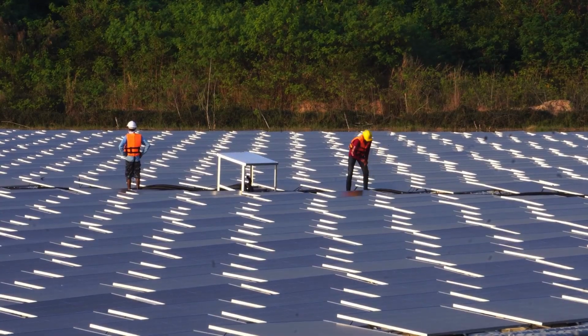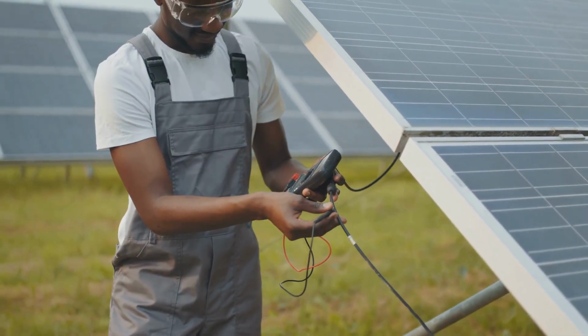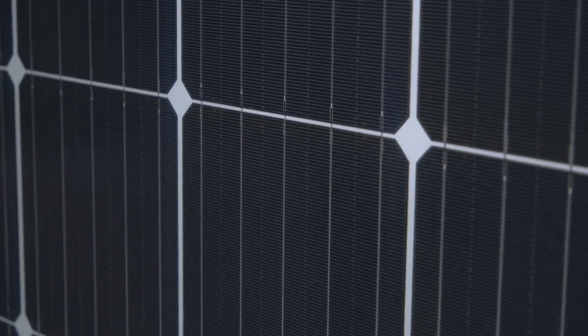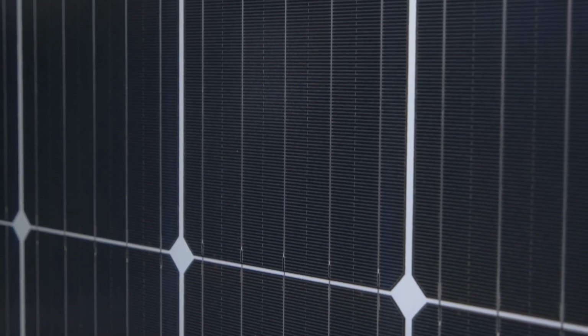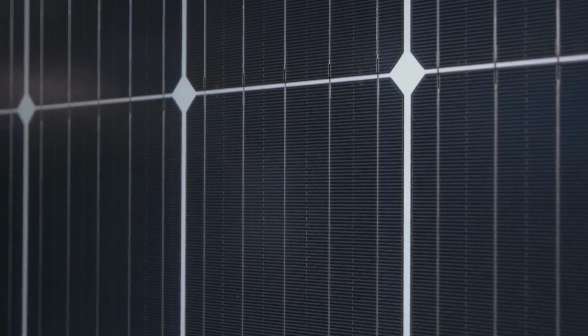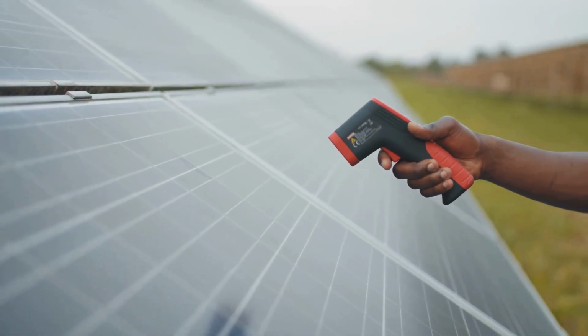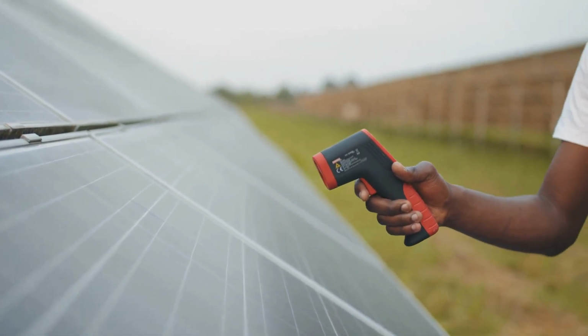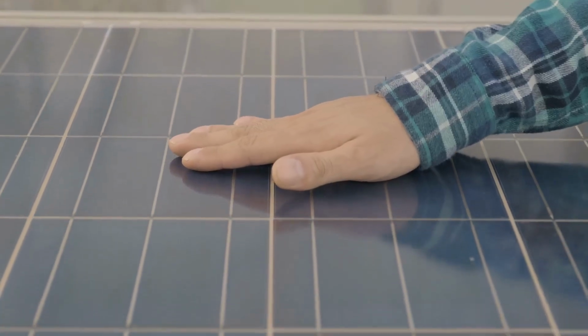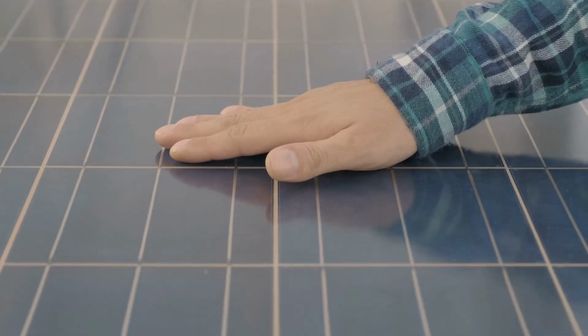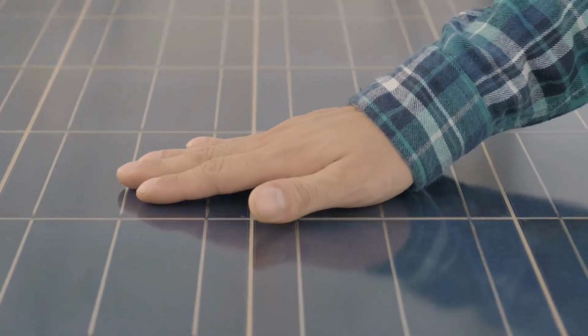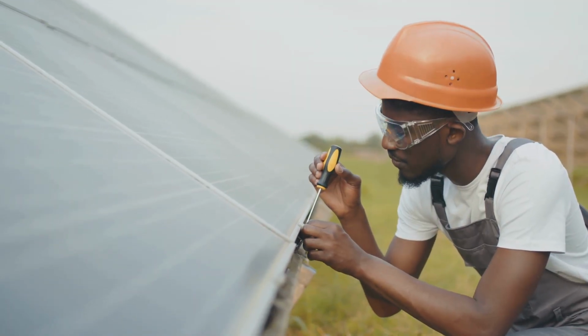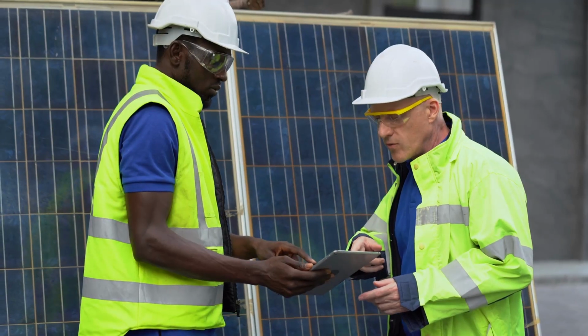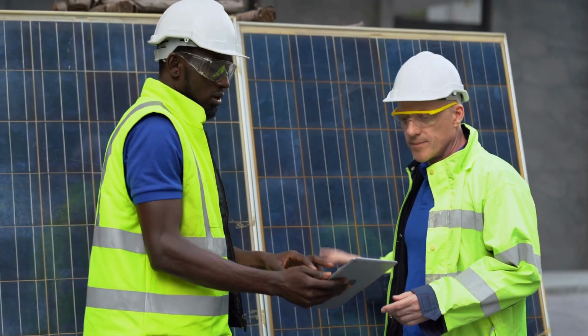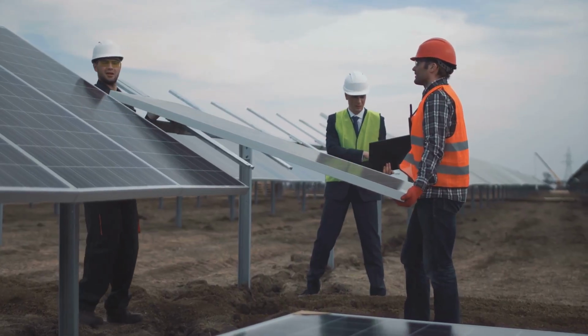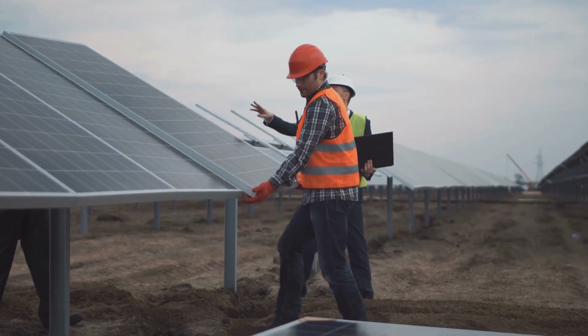Efficiency alone does not guarantee adoption. Tandem panels introduce new ways they can fail. If the perovskite layer degrades faster than the silicon layer, overall panel performance declines, even though the silicon layer remains intact. Differences in how the two layers expand and contract with temperature can create mechanical stress. The electrical connection between the perovskite layer and the silicon layer must remain stable for many years. Engineers also must manage small amounts of lead used in many perovskite formulations, ensuring that the lead stays fully contained throughout the panel's lifetime and during disposal. These issues determine whether the panels meet certification standards and long-term warranty requirements.